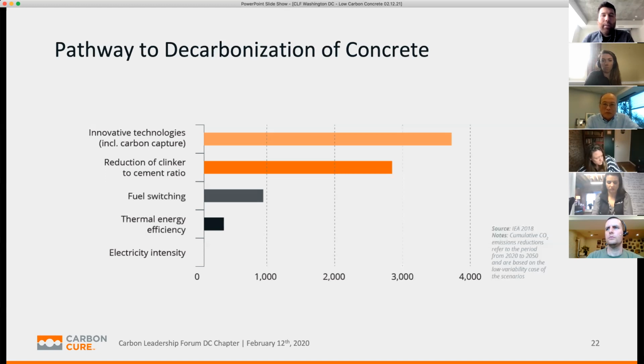So that's expected to be a pretty significant source of reduction, again, focused on just reducing the quantity of cement in the mix. The top one, the lighter orange, is what they call carbon capture, utilization, and storage. So you may not know that term. If you do know that term, you might be thinking of some of the news around people capturing CO2 and pumping it underground and storing it in a big former oil and gas reservoir. So that's the same concept, but the idea here is basically, can we divert CO2 that has to be manufactured and keep it from entering the atmosphere, either by putting it somewhere where it can't do any harm or using it to make new products? So that's really the key thing here.